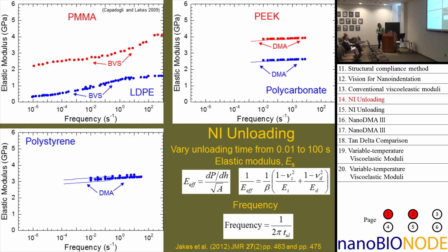And I saw that indeed, so I calculated effective modulus in the usual way, the initial unloading stiffness divided by the square root of area, and then using the standard Hertzian contact equation to calculate an elastic modulus. And then I estimated frequency as just 1/2π times the time of the unloading. And when you do these experiments carefully, one of the things you have to make sure is that the unloading slope is actually an elastic response, so that you don't have some forward viscous deformation happening. But if you go through and carefully analyze the data, what you find is that systematically, these nanoindentation results are always higher than the conventional analysis. But what's interesting here, from the aspect of trying to understand whether these mechanical properties are related to microphysical processes, is that the shapes of the curves are quite similar.